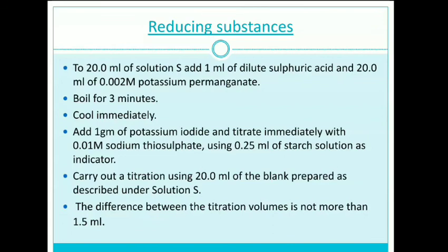You have to carry out the titration using 20 ml of a blank also, which is prepared as described under solution S, and you have to measure the difference between the titration volumes, and it should not be more than 1.5 ml. If it is not more than 1.5 ml, then you can say that the test passes, otherwise the test fails.